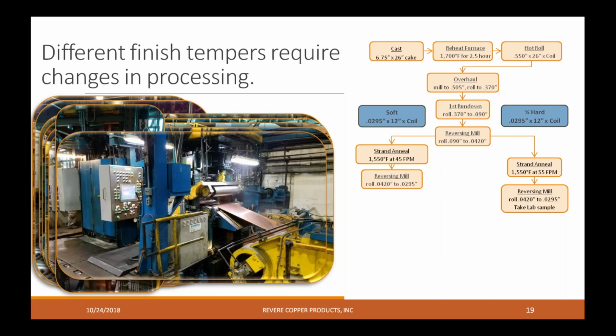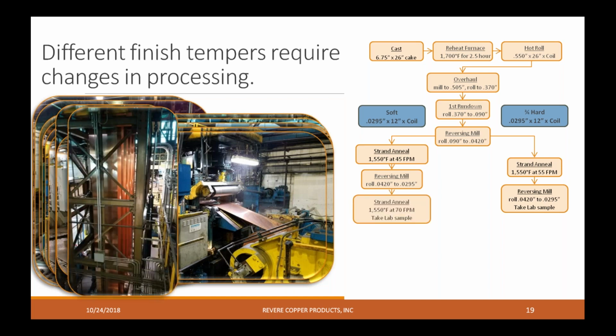So then the next step would be to finish the gauge. So it's going to get rolled again, and this is cold rolled. And on the left side and the right side, you're going from 0.042 to 0.0295. On the right side, it's done. It's at its final gauge, and we send it to the lab for testing to make sure it meets its temper requirements. On the left side, it still needs to be annealed again because this was ordered soft. And in that case, it's annealed at 70 feet per minute, so much slower.